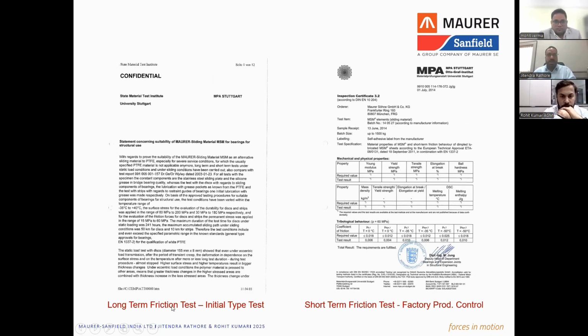This is the long-term sliding test, which is a 50-kilometer slide test on the approved sliding material, done for its qualification. In this 50 kilometers of sliding, three parameters are continuously changing. One is the pressure, which changes from 5 MPa to a full 180 MPa. The other is the speed of sliding, which changes from 2 millimeter per second to 15 millimeter per second, and again comes back to 2, then changes again.